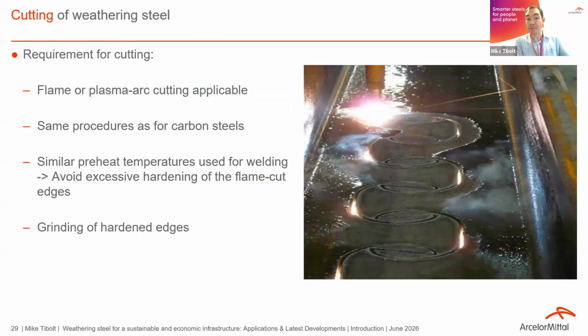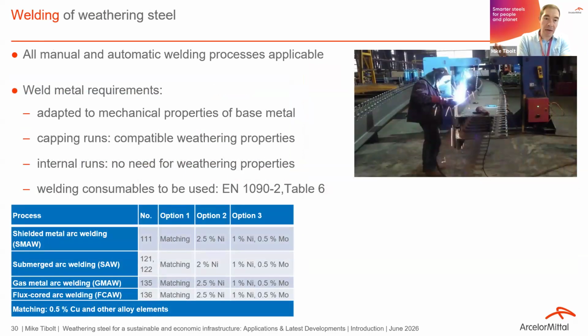For the cutting, flame and plasma cutting can be done according to normal non-weathering steel, so it's the same procedure as for carbon steel. It's also a similar preheat temperature that you should apply for welding, to avoid excessive hardening of the cutting edge. And of course, you should grind the hardened edges to avoid any cold cracking afterwards. For welding, all manual and automatic welding procedures are applicable, so there's no limitation.